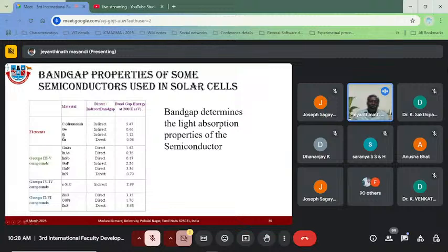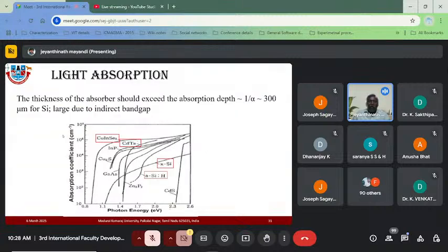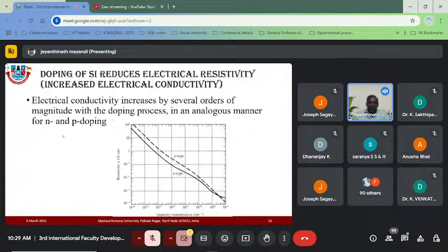And silicon has been proven to be utilized not only in terrestrial applications but also in space applications. And this is another point: the thickness of the absorber should exceed the absorption length. This is large due to the indirect band gap, for example in silicon. So that's why most silicon solar cells are made in the range of 300 micrometers. That is the main reason. If you reduce the thickness, then the photons will transmit through the wafer, which is another issue. So you need to use silicon wafers at least 275 to 300 micrometers thick. I think this is some of the information.